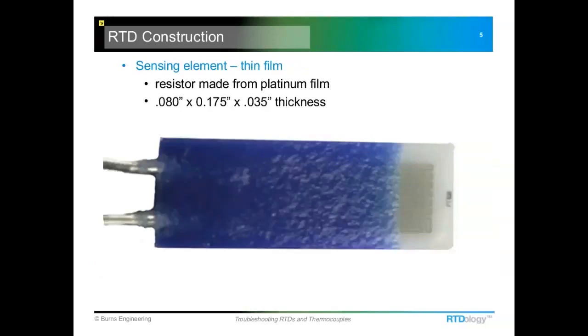The other common type of platinum sensor is thin film. Looking at this photograph, you can see this little ceramic substrate, and then you can just barely see these little gray tracings on here. That's the actual platinum that was deposited on that substrate. The external lead wires are connected to that little platinum tracing, and then it's covered with a glass material to secure the lead wires to it. This kind of sensor can be extremely durable. As you can see, the platinum can't really move around a whole lot on that substrate, and the glass holds the lead wires very securely to the substrate and the platinum tracing.